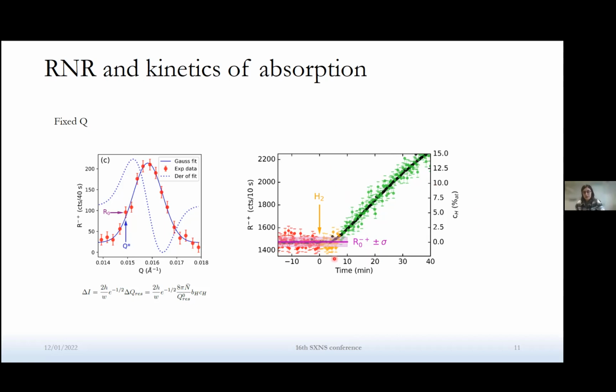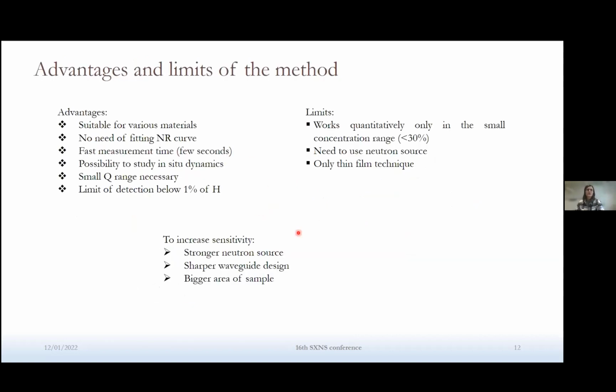So what I want to mention is that if you see here, we were able to detect around 1% of hydrogen with a step of 10 seconds, which would be basically impossible if we employed only conventional NR. So, of course, there are some drawbacks, which is that we need to perform also conventional NR to calibrate thickness changes or inhomogeneity in the sample, which is very important. But this method allows very good sensitivity and allows us to study very fast kinetics in various materials. All we need is a contrast between the material of interest and the substrate, SLD contrast.